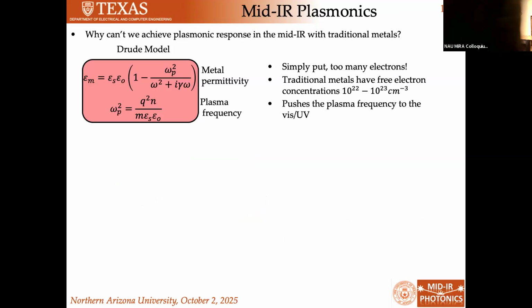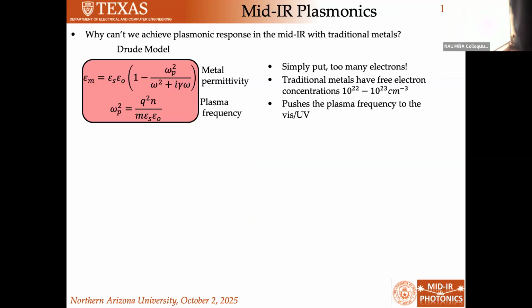So if we look at how to describe the optical response of a metal, the way that we typically do this is with the Drude model, right? You can do a Drude model by treating electrons using Newton's laws, and it's a really nice derivation you'd give to a junior-level student in E&M. You can calculate the permittivity given a scattering rate as a function of frequency, and it depends on the plasma frequency. The plasma frequency is the frequency at which your material's permittivity goes through zero.